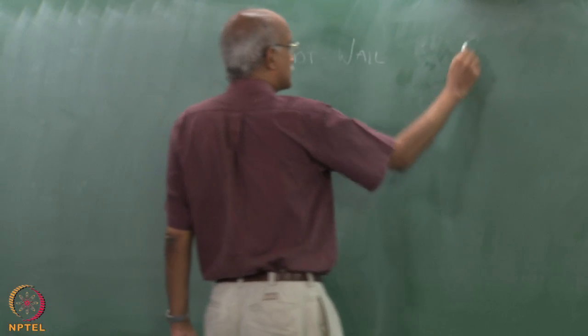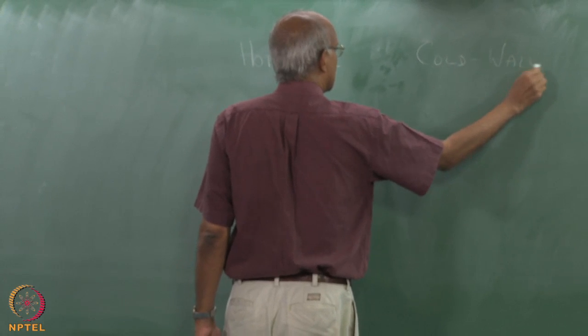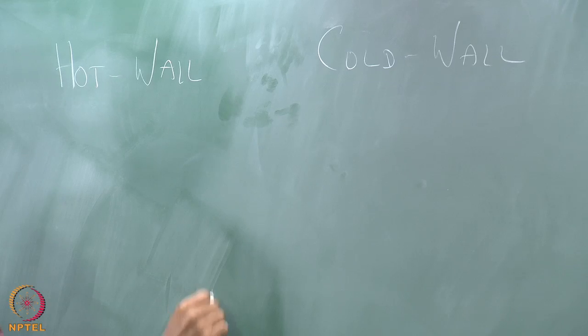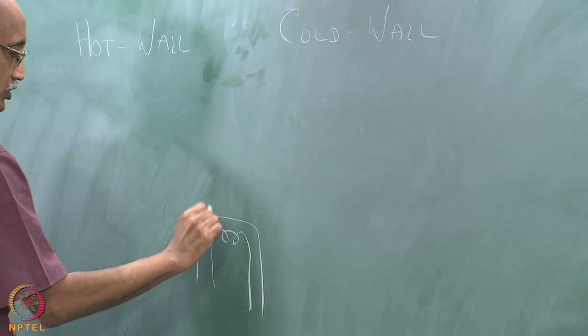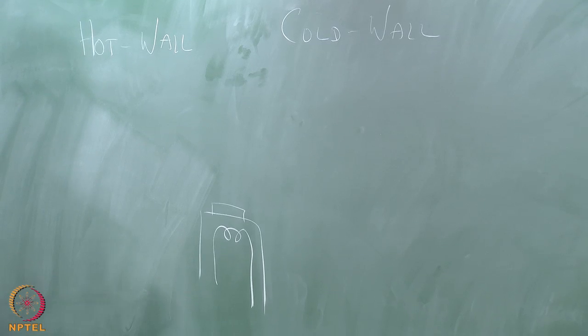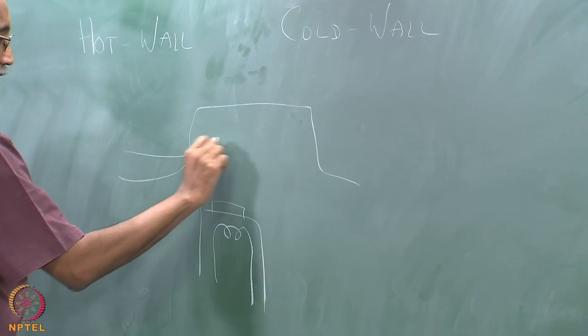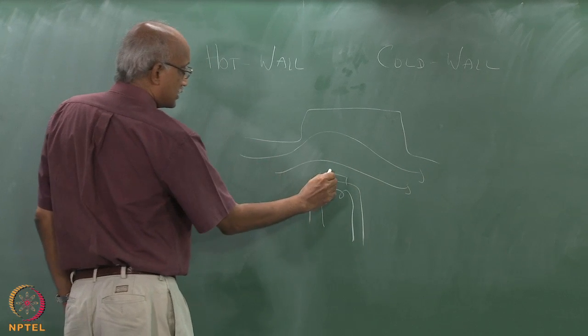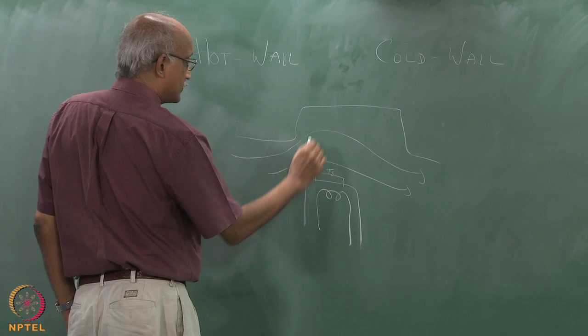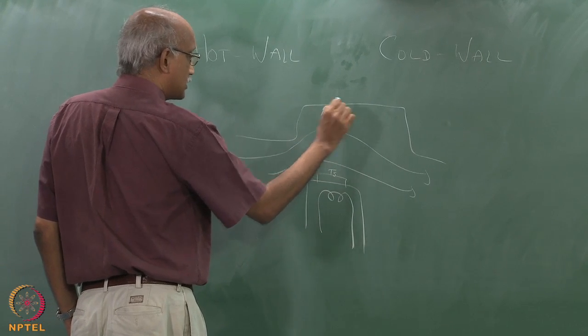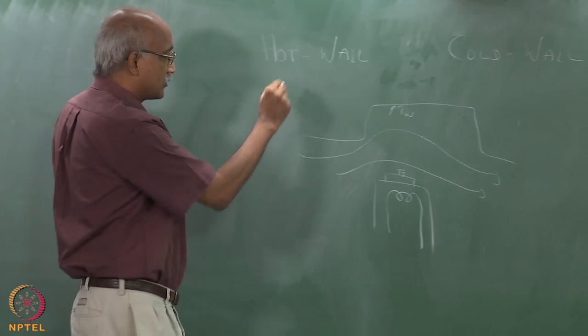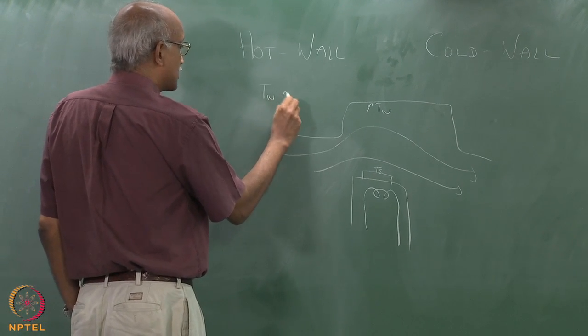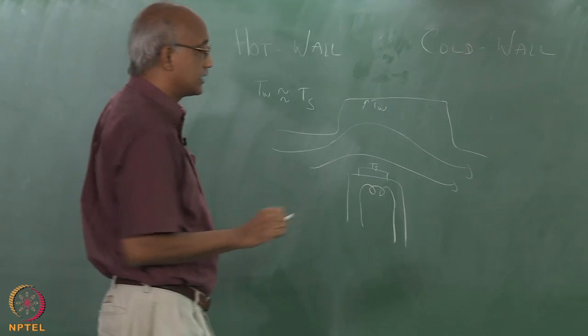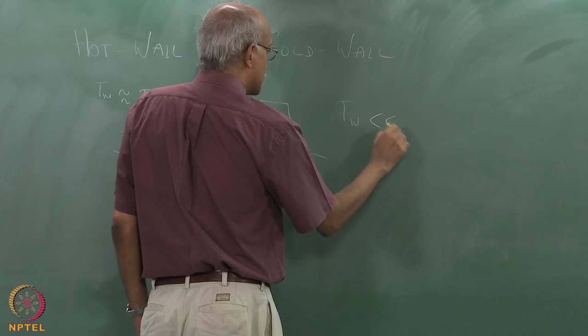One is known as a hot wall reactor, and the other is known as a cold wall reactor. Now, the difference between these two is, you have the substrate which is being provided with an external energy source on which you are depositing the film, and you have the reactor and the gases flowing through the reactor. Now, if the substrate temperature is some, let's say, TS, and let's say that the walls of this reactor are at some temperature TW, in the case of a hot wall reactor, TW is approximately equal to TS, and in the case of a cold wall reactor, TW is much smaller than TS.